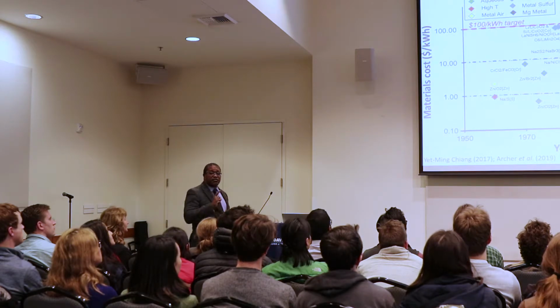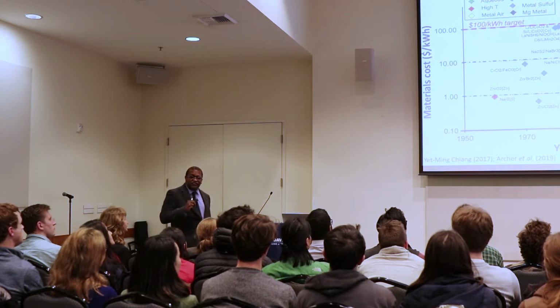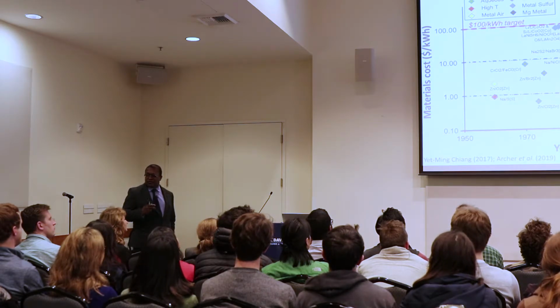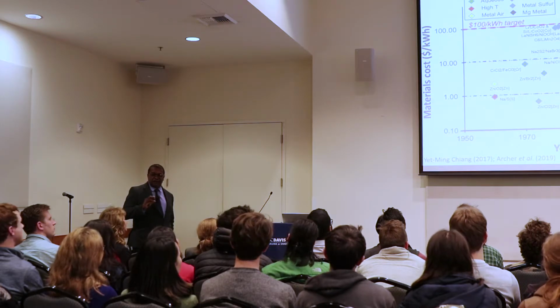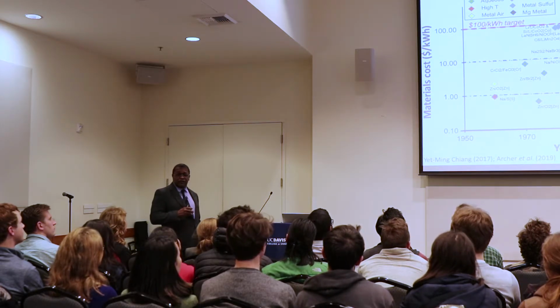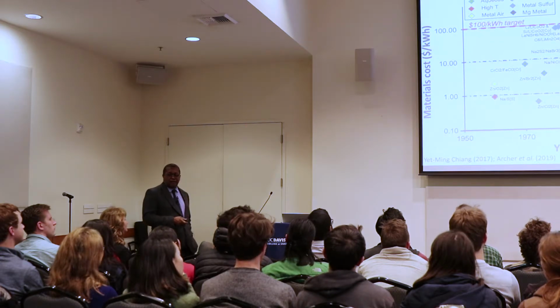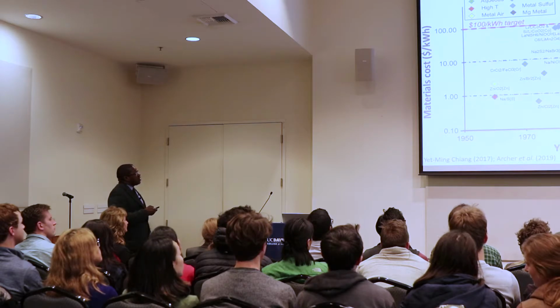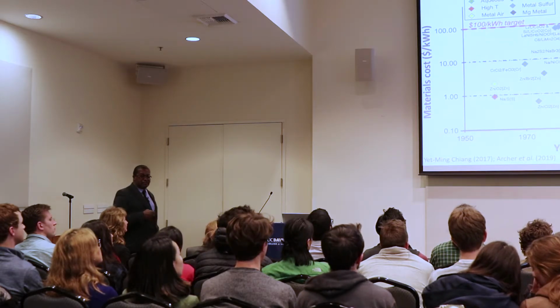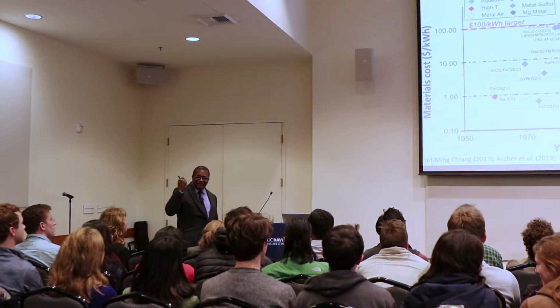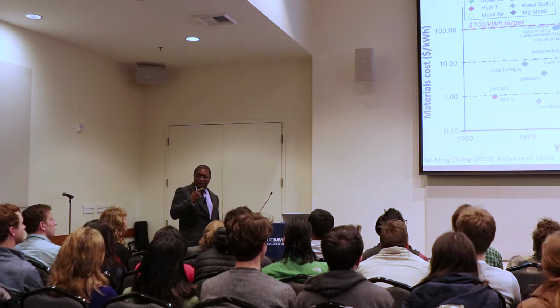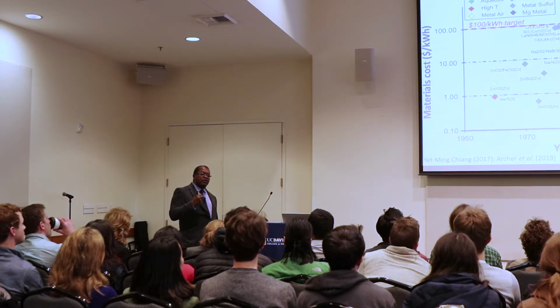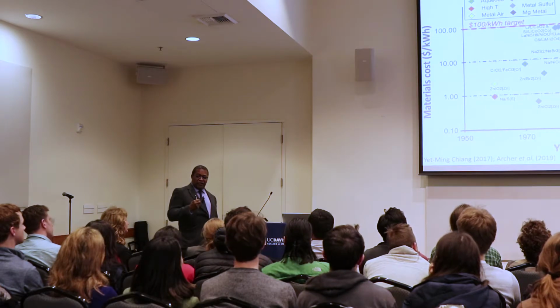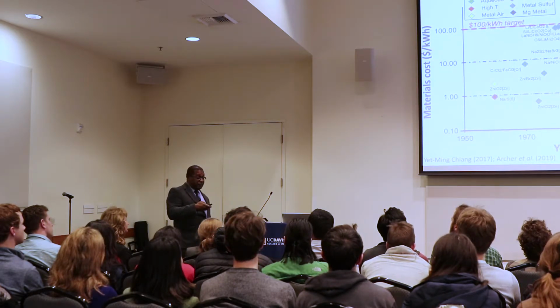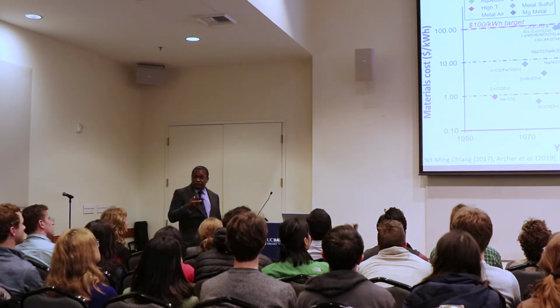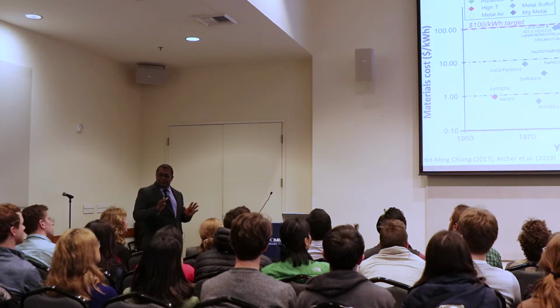Now notice the y-axis is a materials cost. The reason for that is about 60% of the cost of a battery is the materials cost. So this cost doesn't decide everything, but it certainly decides a pretty substantial fraction of the overall cost, and so it is thought to be a good barometer of the cost characteristics. Now, this $100 a kilowatt hour, if you compare it to the 5 or 2 cents a kilowatt hour for generation, is a non-starter. But because a battery is a closed system, if that system can operate for 1,000 cycles trouble-free, then the amortized cost becomes 100 over 1,000, and so it becomes competitive.